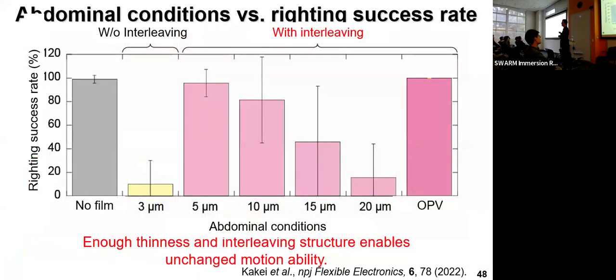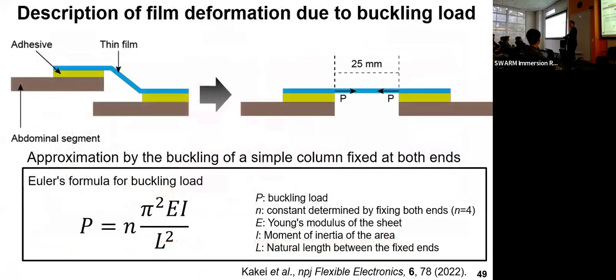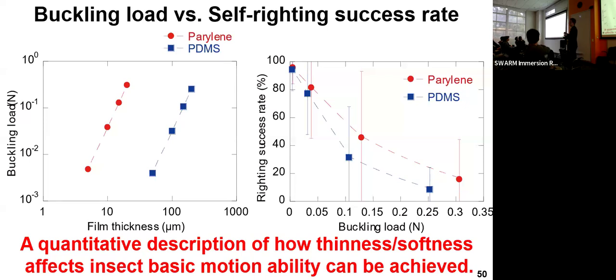Here is the summary. You can see the very clear thickness dependence of the righting success rate. Okay. Then we try to describe this more physically using a buckling load model. Here we replot the success rate as a function of the buckling load with different film materials and different thicknesses. And you can see that there is a very good relation between the buckling load and righting success rate with different materials. The harder Parylene and softer PDMS both show almost similar threshold values around